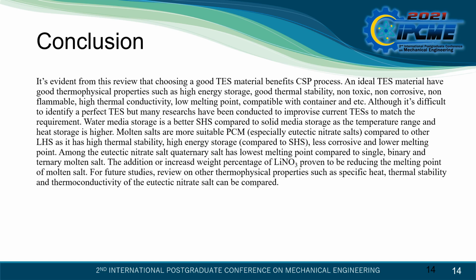Molten salts are more suitable PCMs, especially eutectic nitrate salts, compared to other latent heat storage, as they have high thermal stability, high energy storage, are less corrosive, and have a lower melting point. Among the eutectic nitrate salts, quaternary nitrate salt has a lower melting point compared to single, binary, and ternary molten salt. Increasing the weight percentage of lithium nitrate has been proven to reduce the melting point of molten salt. For future studies, we can review other thermophysical properties such as specific heat, thermal stability, and thermal conductivity of the eutectic nitrate salt.